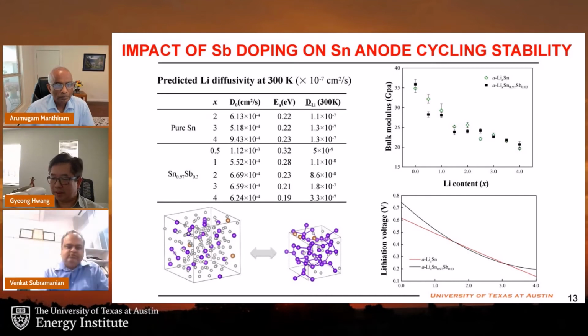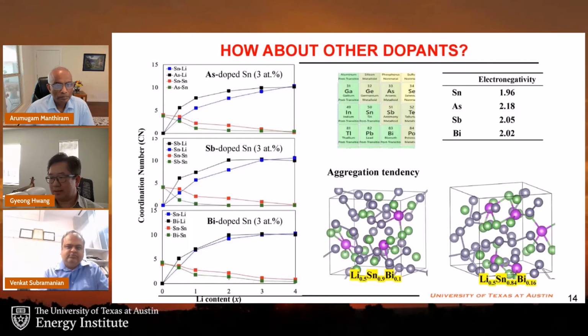So we have also examined the other dopants in the next slide, such as the arsenic and the bismuth. As you can see here, arsenic, antimony, and the bismuth are in the same family, but they have different electronegativities. So as briefly shown here, the lithiation behavior of tin varies with choice of dopant. So our work suggests that the performance of tin-based anode can be enhanced via fine-tuning of doping. Okay, the next slide.